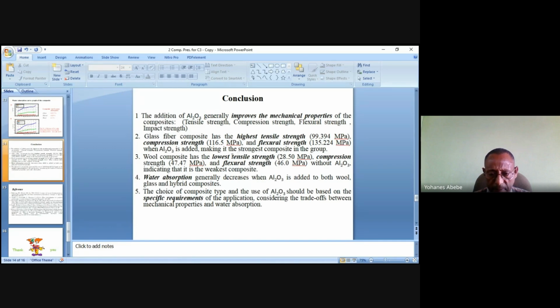So there are some improvements as a result of hybridization. At the same time, nano enhancement improves the properties of the composites. The water absorption generally decreases when alumina is added to the wool, glass, and hybrid composites. So the choice of composite type and the use of alumina should be based on the specific requirements of the application, considering the trade-offs between the mechanical properties of.